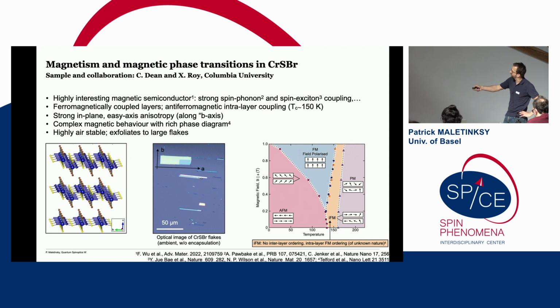I should also say, and I forgot to say that within this plane, actually, there is a preferred axis, so it's not a fully isotropic in-plane magnet. It has a preferred axis, and it turns out to correspond to one of these cleavage axes. The B axis is where the magnetization naturally wants to point to.